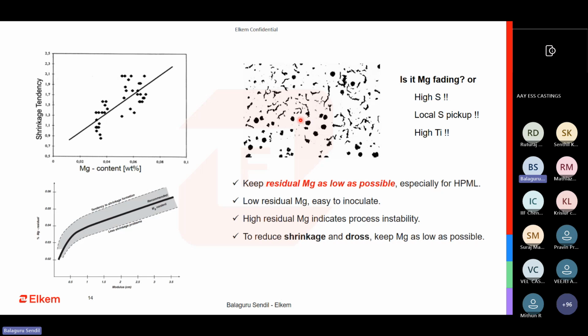If you are consistently operating at a residual Mg of 0.035 to 0.04, and suddenly on a particular day you have compactedness in your microstructure, I would focus on what happened. Is there a sulfur pickup by mistake in the base metal itself, or from the sand or coating? Or is there a high titanium contamination, either from the pig iron, the recarburizer, or the coating? This is the area I would focus on. If you only have vermicular structures, that indicates the magnesium has faded or something has happened that made the magnesium ineffective.